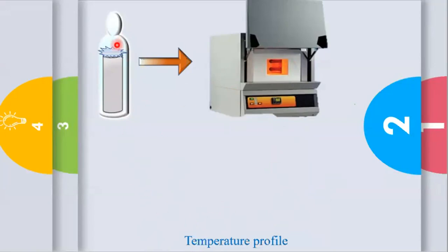By centrifugal force, the flux will come out and it will accumulate somewhere here. So at that temperature, the flux will be liquid, but your sample will be solid. As the crystal has been formed inside, that will be in solid form and inside the ampule. But the flux is in molten state, which can be extracted by centrifugal force. I see.